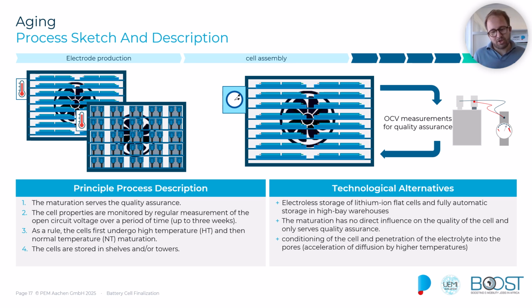First, we want to make sure that in that process we have a maturation which serves certain quality assurance. So we want to regularly measure each cell's open circuit voltage, the OCV, while in storage. And if an OCV drops faster than a specific rate, it would indicate a certain self-discharge or an internal leakage or problem, that the cell might be defective and should be scrapped. So that's often called voltage monitoring for potential failure detection.